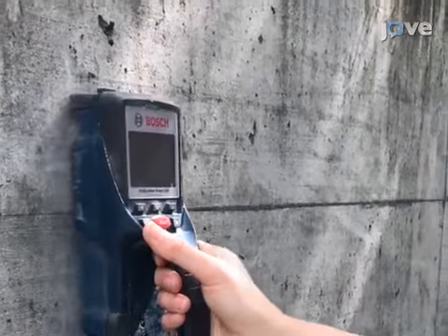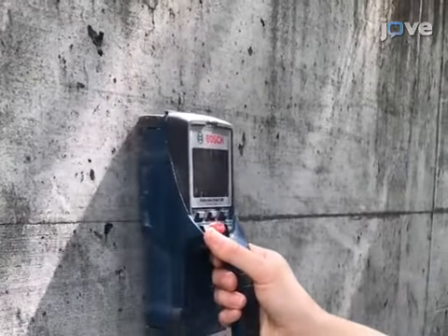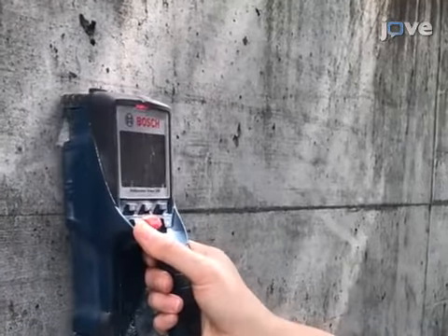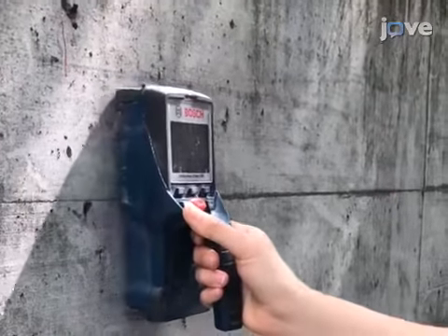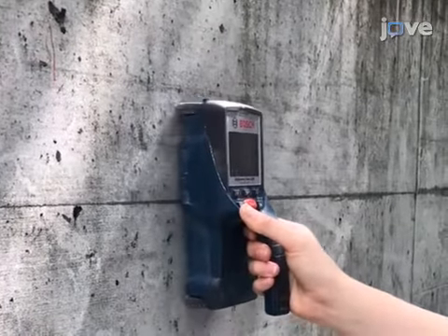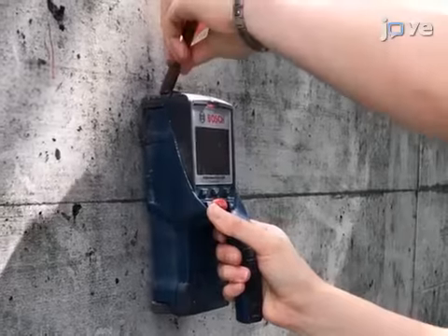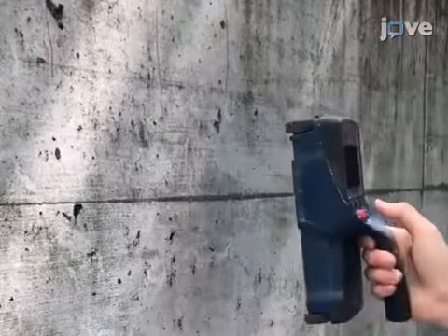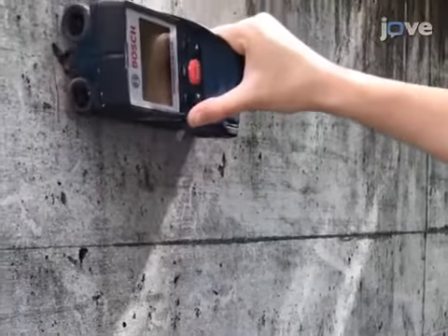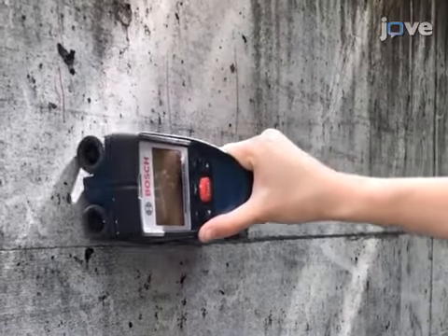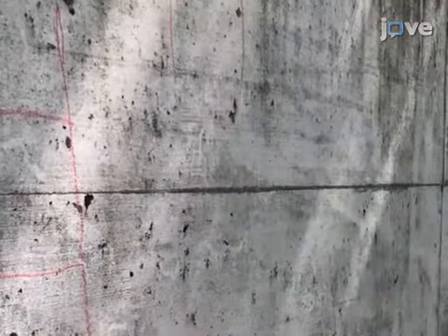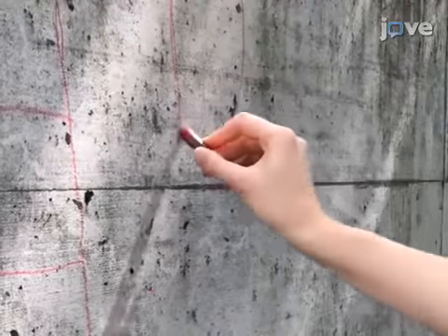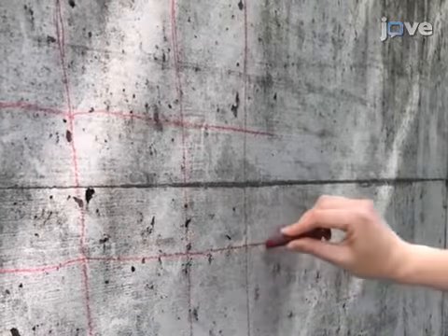Begin by selecting test areas in the concrete structure as described in the text protocol. Locate the reinforcing steel bars in the concrete by means of a non-destructive handheld scanning device commonly known as a reinforcing steel detector. Move the steel detector both in horizontal and vertical directions over the concrete surface within the test area. Using chalk, mark each reinforcing steel bar temporarily in a grid shape on the concrete surface.